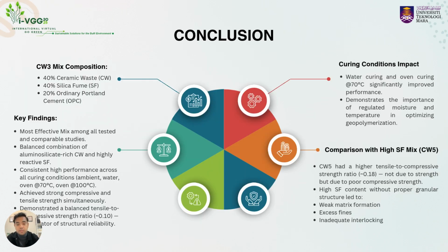As a conclusion, CW3 offered the best overall performance regardless of curing method. Water and thermal curing at 70 degrees Celsius significantly enhanced strength. This balanced mix achieved a reliable tensile to compressive strength ratio of 0.1, an indicator of structural integrity. The high silica fume alone was insufficient without granular support from CWP. This research demonstrates the viability of industrial waste materials in creating durable, eco-friendly construction alternatives. Thank you for your attention.